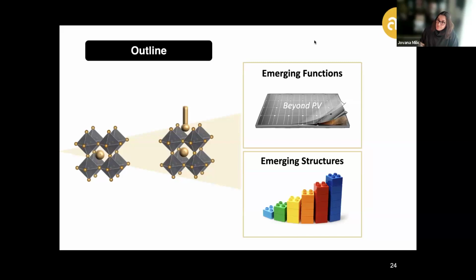In general, these were enabled by providing intricate atomic level understanding of the nature of the interactions between the underlying components, which set the basis for going beyond the use of small molecular modulators at the interface with hybrid perovskites—often in substoichiometric amounts—to fully incorporating them within the extended hybrid perovskite frameworks.